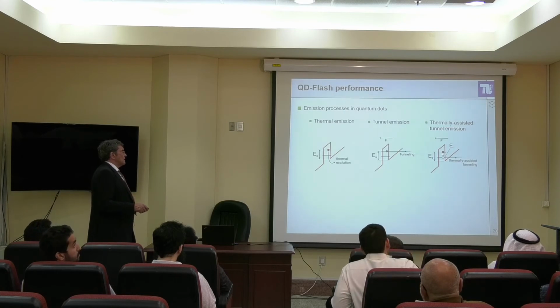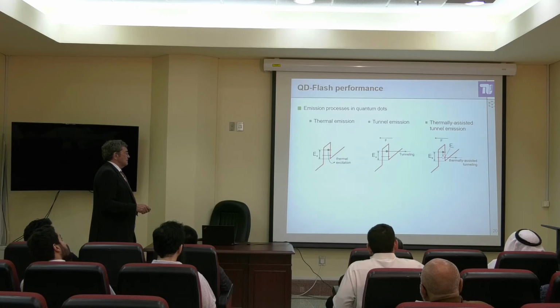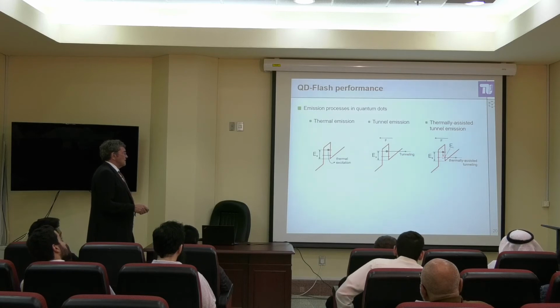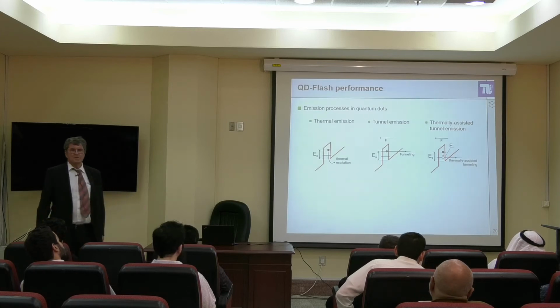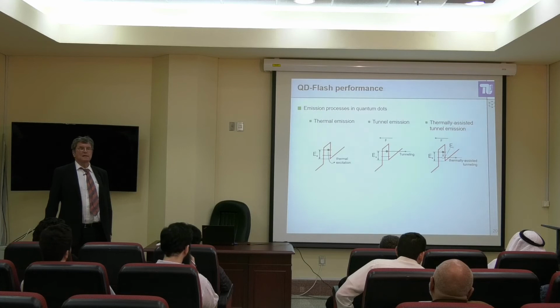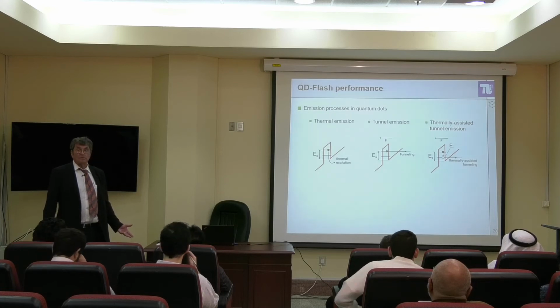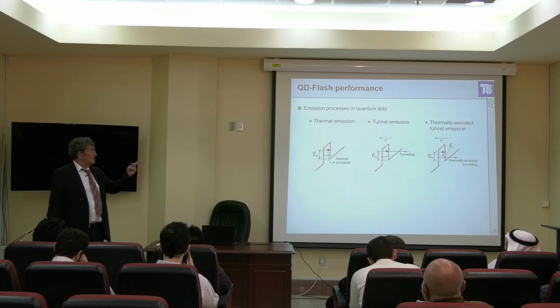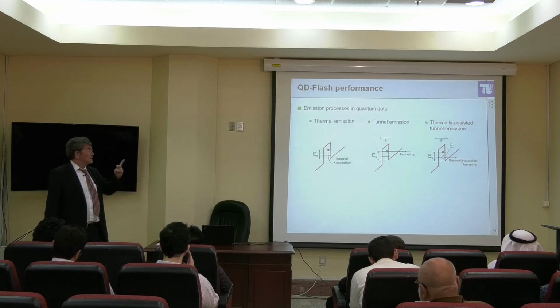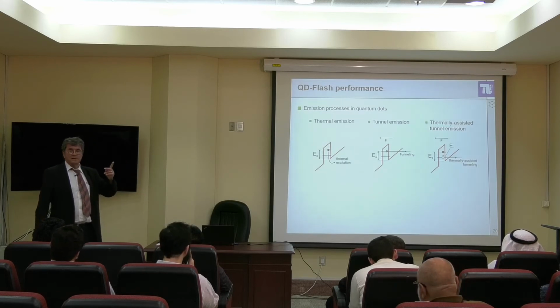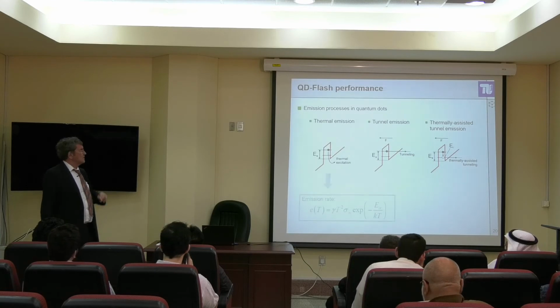And then it goes only to the excited state. The energy difference is much less for holes, and the barrier is smaller, and then you have thermally assisted tunneling. So what you really have to do when you design is look at that third point, thermally assisted tunneling. You have to design in such a way that this is also not happening.